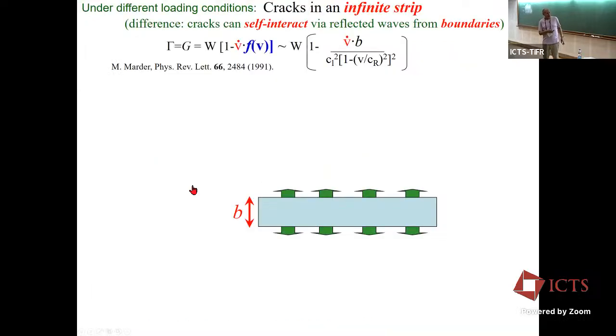If we have different geometries, suppose we break a system like this, which is an infinite strip. It's a long strip, but it has vertical boundaries. So the crack, as it's propagating, can send out waves. The waves bounce off the boundaries and come back and interact with the crack. In this case, the crack has to have inertia because it knows about what it did beforehand. Information is not being propagated out to infinity as in an infinite system, but it's bouncing back and interacting with the crack. So the crack's history is coming back and interacting with its present.